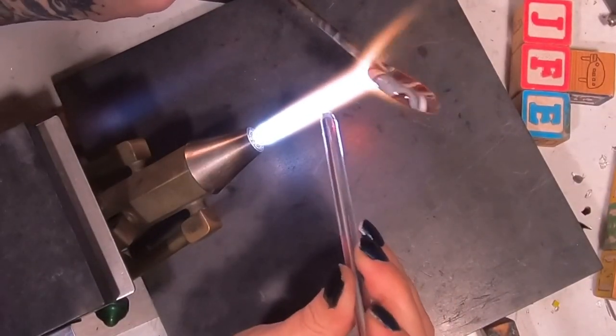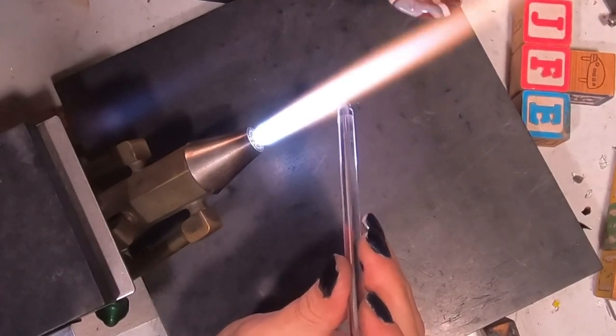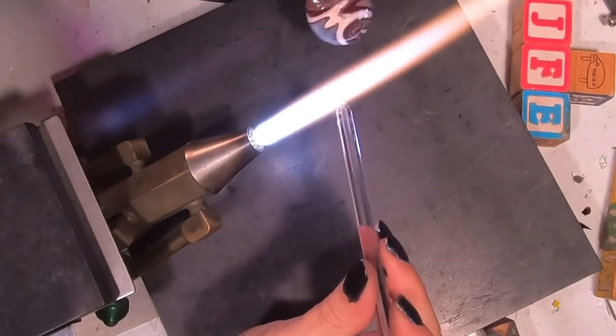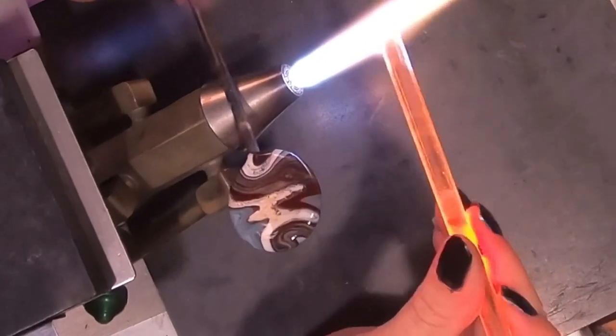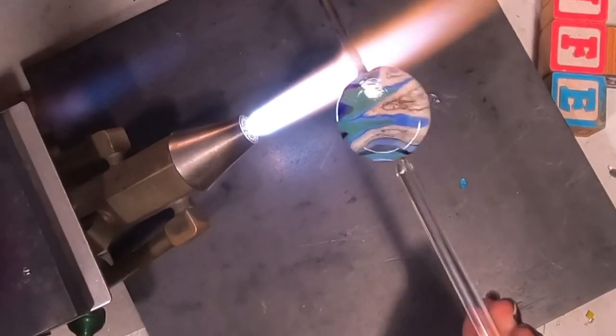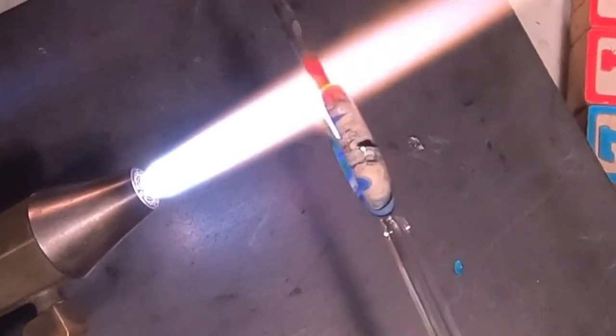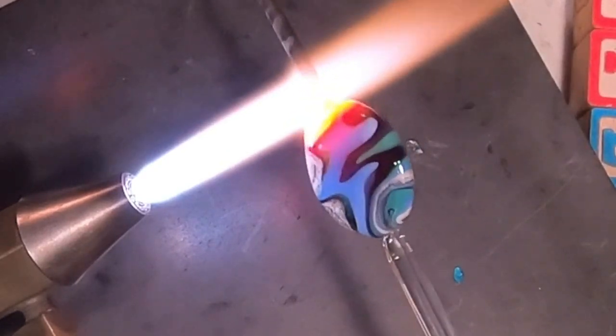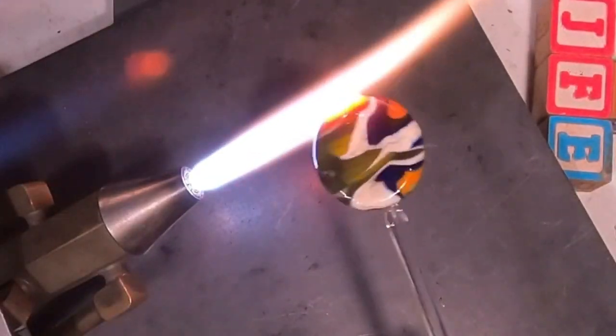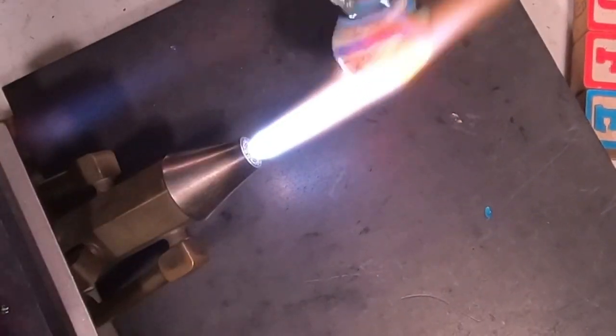So we're going to add the punty. When I do a punty it's just a matter of heating up the very tip of the glass and rolling it into a slight pencil point. I like to wait until all of that hot color of the glass goes away, and when you press it onto the bottom of your glass you want it to feel like a stiff taffy — that will allow you to take the rod off, or the punty rod, off without any problems.